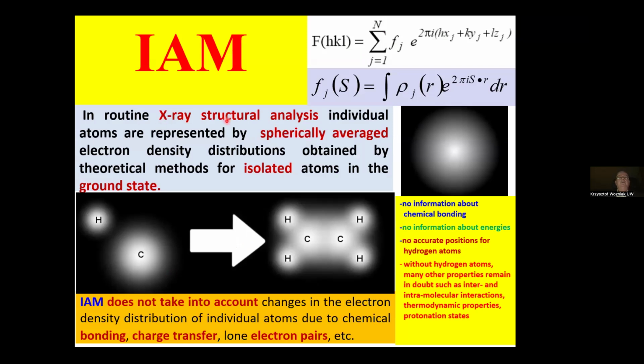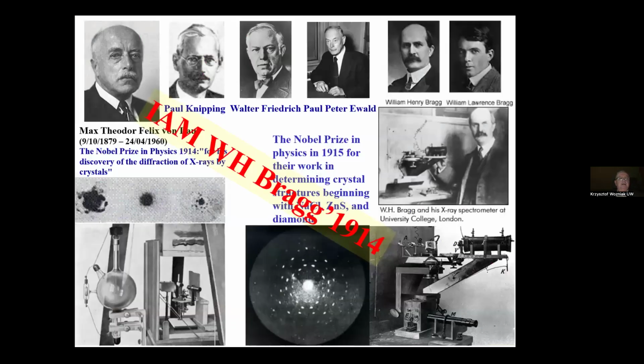In this kind of procedure, in routine X-ray structural analysis, individual atoms are represented by spherically averaged electron density distributions obtained by theoretical methods for isolated atoms in the ground state, and atomic scattering factors are just a Fourier transform of spherical atomic electron density. The independent atom model does not take into account changes in electron density distribution of individual atoms due to chemical bonding, charge transfer, lone electron pairs, and other effects. So that's the simplest possible model of atomic electron density.